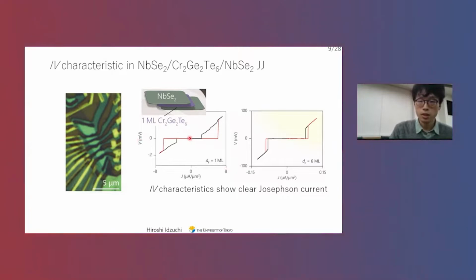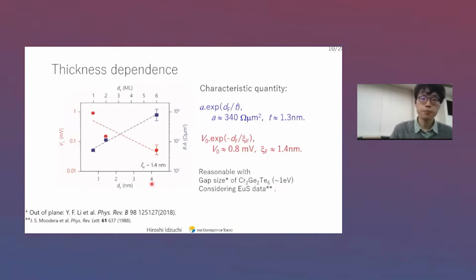So you see a very clear zero resistance state. That means we have indeed Josephson coupling between two niobium diselenides across this monolayer CGT or six-layer CGT. If you bias more, at some point you break this, the energy exceeds the Josephson coupling, and then you have the normal state. So you have the usual resistance of the junction. So first we confirm the Josephson current, and then we also study the thickness dependence and characterize the thickness characteristics.